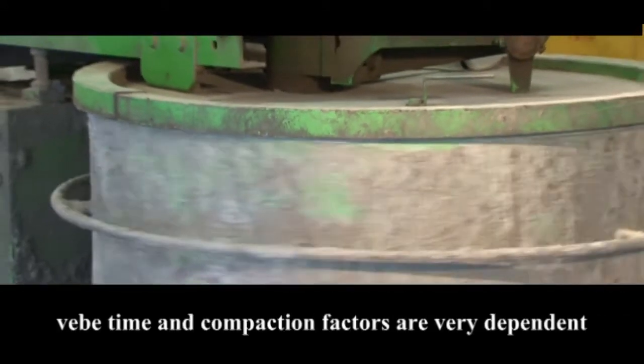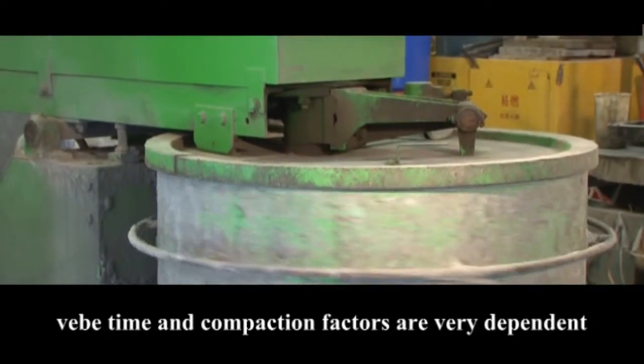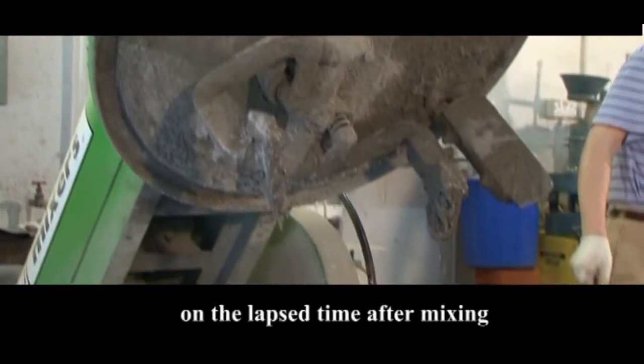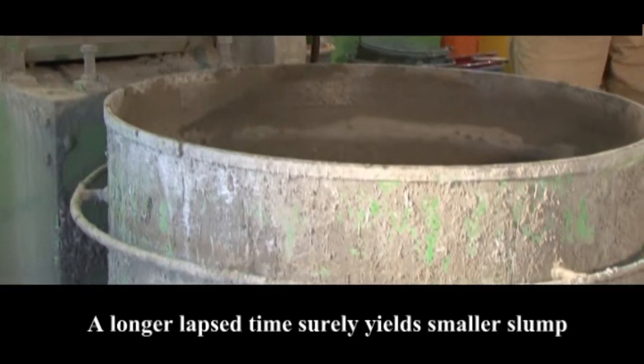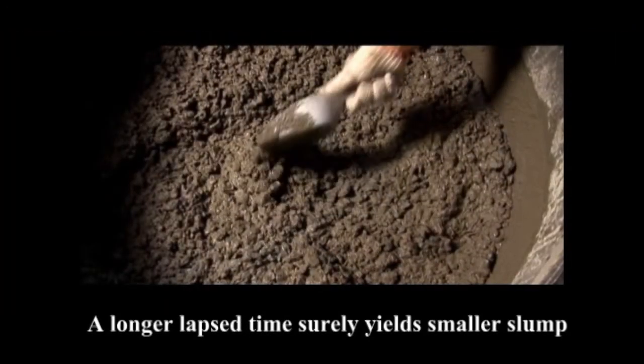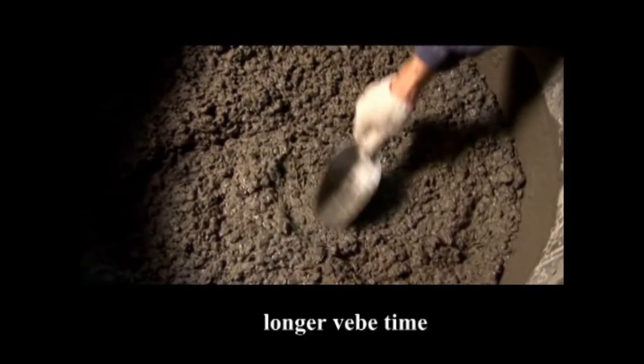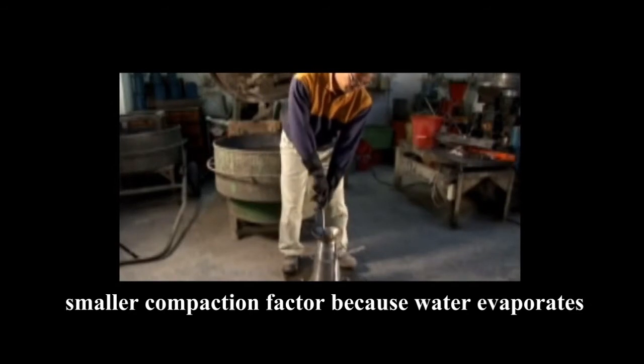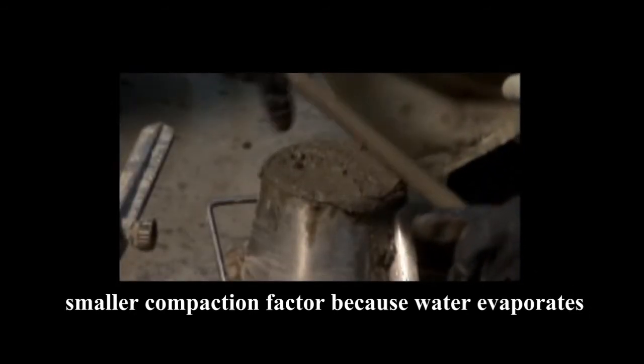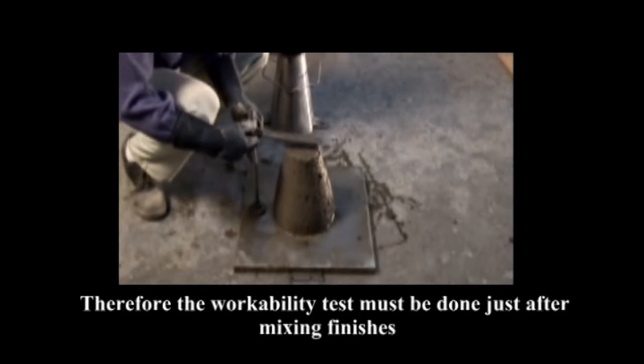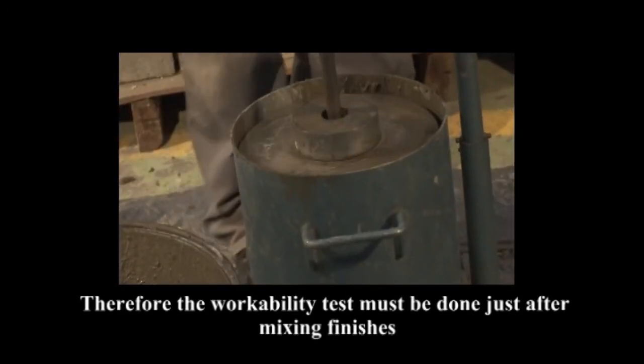The slump values, Vebe time, and compaction factors are very dependent on the lapsed time after mixing. A longer lapsed time surely yields smaller slump, longer Vebe time, and smaller compaction factor, because water evaporates. Therefore, the workability test must be done just after mixing finishes.